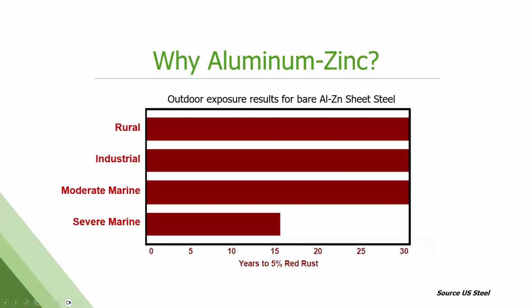So there's just some comparisons in different conditions. So rural, industrial, and then moderate marine and severe marine. This is years to 5% red rust. So how long is it taking for that metallic coating to wear away, be sacrificed to get down to the base steel? See that we're 30 plus, even in moderate marine, and in severe marine, and this is unpainted, you can get to at least 15 years or longer before rust is a problem. So it's a really good product for marine locations, especially if you combine it with a marine paint system on top of it.